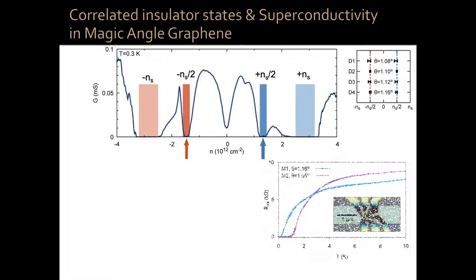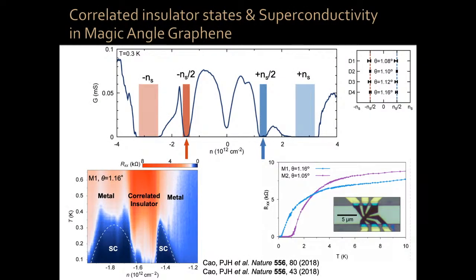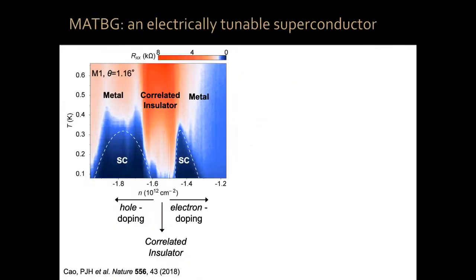Then an even bigger surprise happened, okay? So what happened is that if you add a few electrons or a few holes with respect to this insulating state, magic angle graphene became a superconductor. You measure the resistivity of the system as a function of temperature, and it goes down and then exhibits a precipitous drop to 0, okay? Not only that, in a phase diagram of temperature versus charge density, we can see that this superconductivity is electrically tunable. Let me show you here a zoom in, okay? So magic angle twisted bilayer graphene is an electrically tunable superconductor, and there are very few of those. There are not so many, okay?